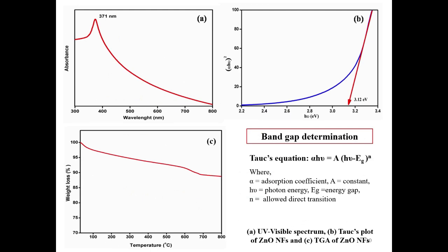This is the UV visible spectrum. UV light is absorbed at 371 nanometer, which is an indication of the formation of a very fine size of nanomaterial. The band gap was determined with the help of the Tauc equation, and it was found to be 3.12 electron volt. It is near to the actual theoretical value of zinc oxide nanomaterial. And we have determined the thermal stability. Zinc oxide seems to be thermally highly stable. It goes beyond 800 degrees centigrade, meaning the material is very stable up to 800 or more than 800 degrees centigrade.